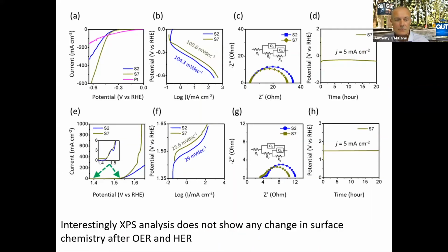If we look at performance, for our hydrogen evolution reaction we're getting really high currents, up to about 600 milliamps per square centimeter, definitely outperforming platinum. Not in the onset potential, but certainly in the high current density regime, we're getting a lot better activity compared to commercial platinum. For the oxygen evolution reaction, we're also getting really high currents, up to about 800 milliamps per square centimeter, which is quite good.